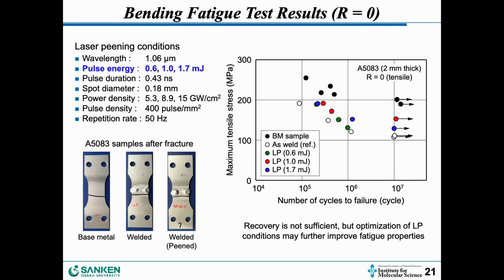So this one is a typical preliminary result of the fatigue testing of the welded sample, the base metal, and the welded sample after laser peening. Laser peening was done with pulse energy of 0.6, 1.0, and 1.7 here, like this. The black one is the base metal sample. As usual, welding decreases the fatigue strength, but laser peening partially restores the fatigue strength. So recovery is not sufficient, but optimization of laser peening conditions may further improve fatigue properties, I think.